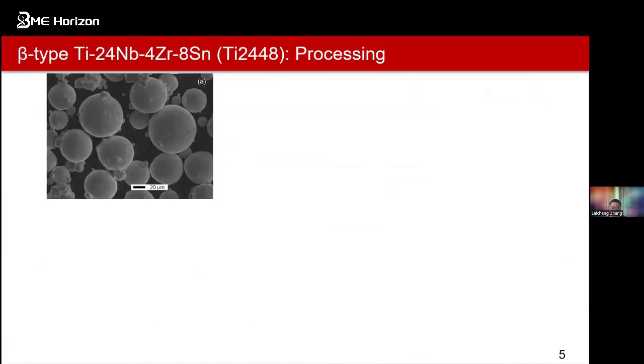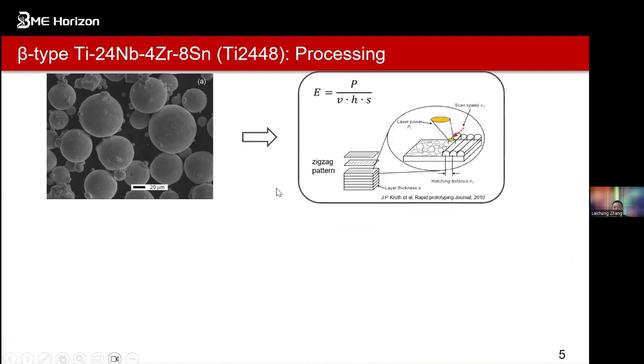So when we try to make anything here, we produce these structures. Of course, you can see that for this kind of beta titanium alloys, most of the composition is titanium. We started from the spherical particles of Ti2448, so titanium 24 niobium, 4 zirconium, 8 tin for this alloy. Of course, from the powders we can produce the structures. We use 3D printing, so they can produce the Young's modulus.